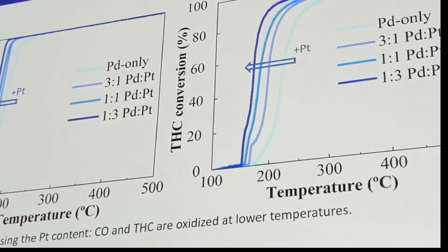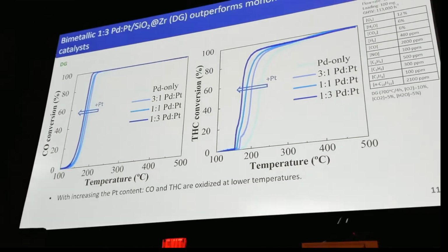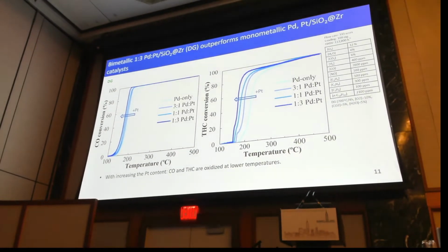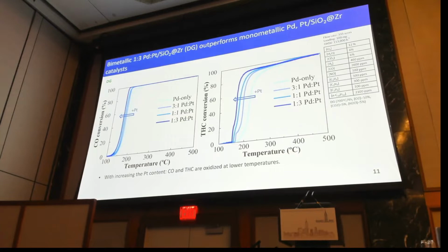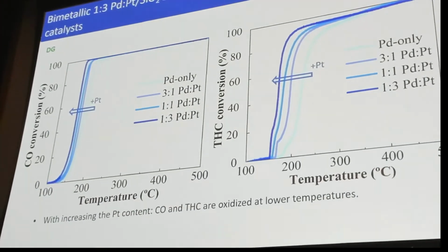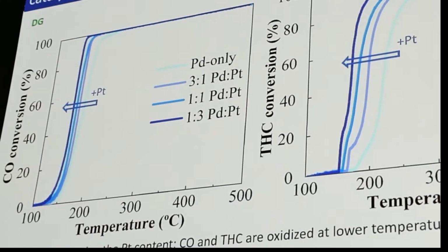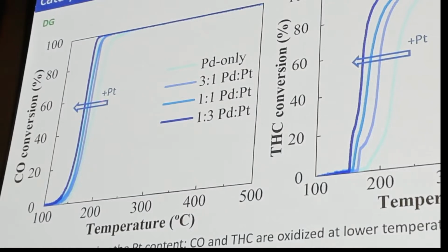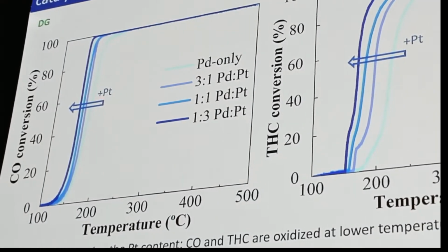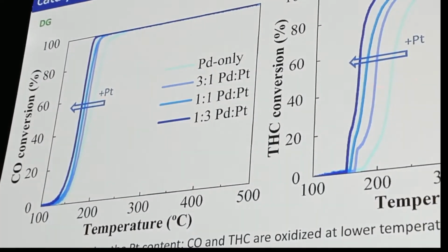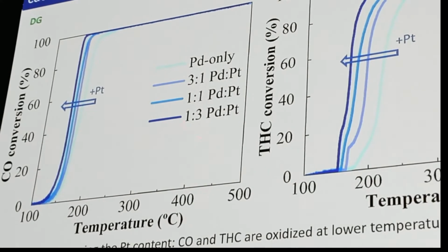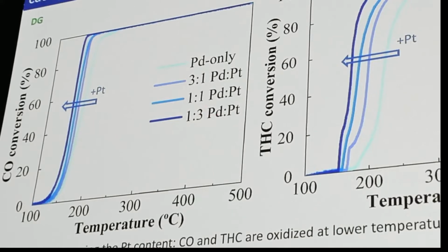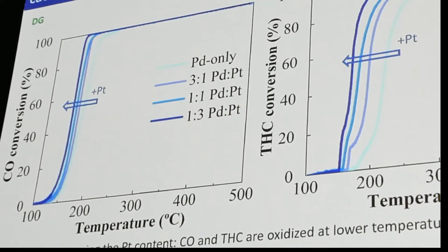So let me show you now how the bimetallic catalysts perform compared to monometallic palladium. The left figure is the CO conversion, and the right figure is the total hydrocarbon conversion as a function of temperature. And this performance is for the degreened catalyst. So what we see here is that when we have platinum in the samples, the performance for CO as well as for total hydrocarbons improves. Particularly the 1 to 3 palladium to platinum catalyst seems to have the best performance.